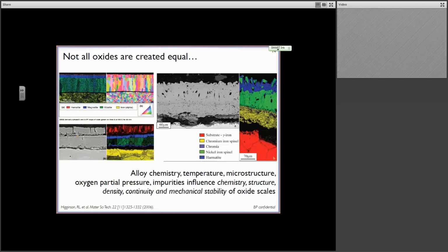And you can look at the color maps, and these color maps tell you the different species, the chemistry, and the orientation of those different oxides. The other big thing that you see is there are big cracks between the alloy and the scale that's forming on top of it, right? So clearly the oxides forming in this case are not necessarily mechanically robust, they're not fully dense, and because of that, they're never going to form a good corrosion barrier or diffusion barrier against any sort of environment that we're interacting with.